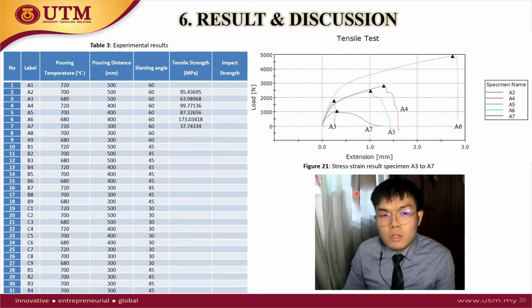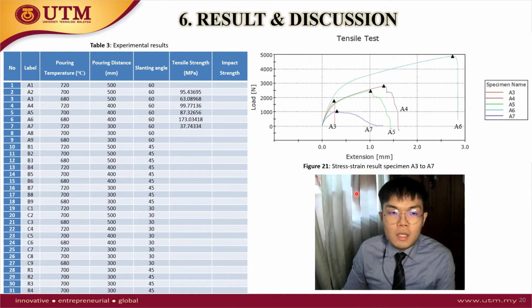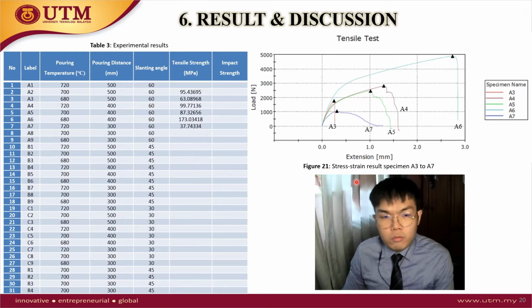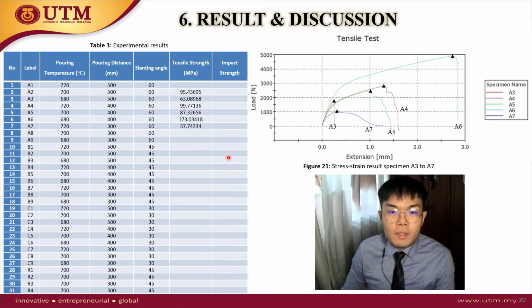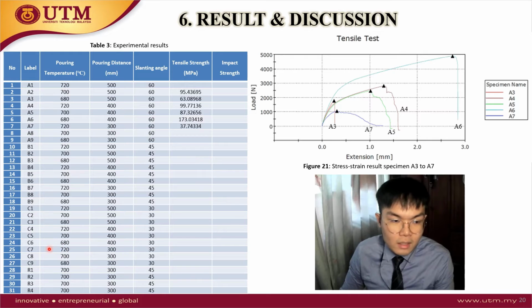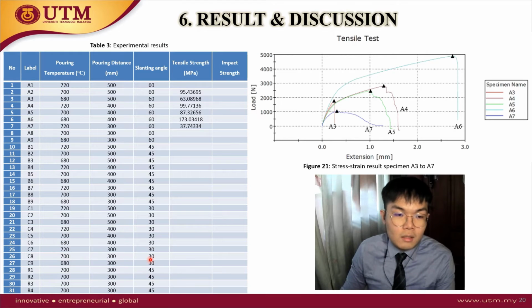Before the lab closure, I was able to carry out the experimental work until halfway. So this is the incomplete experimental result. We have 3 different casting parameters, each with 3 different values, so it's a 3 factorial design, giving 27 sets of casting parameters. And R1, 2, 3, and 4 are the references. And this is the result.